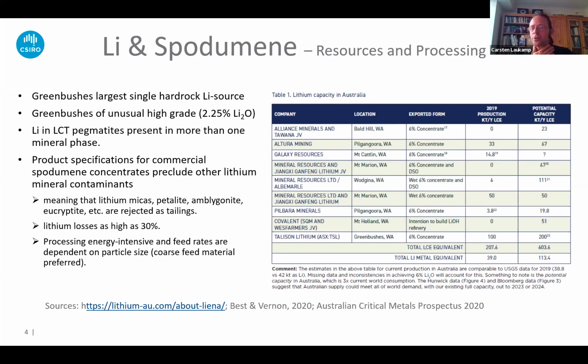What I also just recently found out, and am a little bit disappointed with, is that the product specifications for commercial spodumene concentrates preclude other lithium mineral contaminants. So the clients that are after the lithium want just coarse-grained spodumene. They don't want any lithium micas or petalite or any other funny minerals. So what's happening is that lots of lithium is actually lost and put on a waste dump: 30% of it, even up to 40 or 50% in some deposits.